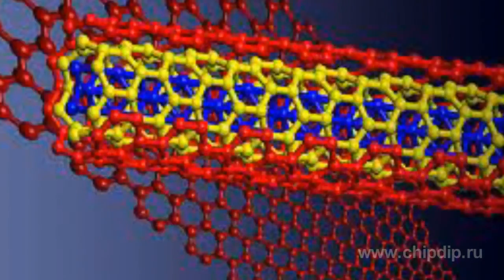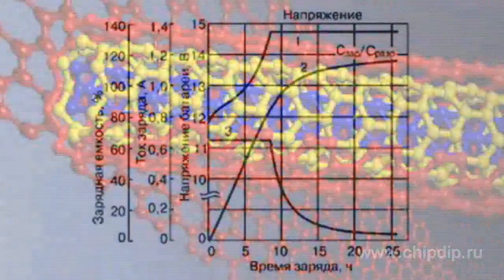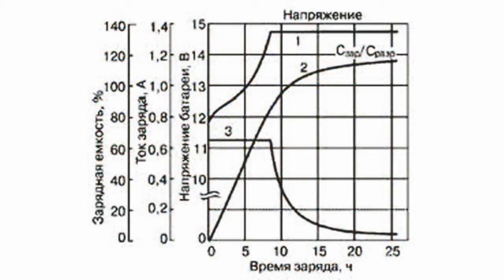The large size of the cavities — about 30 nm high and 150 nm wide — provides free in-leakage of the electrolyte, allowing ion transport of lithium both outside and inside the channels. This significantly reduces charge and discharge time. Additionally, this material has large specific capacity and good cycling due to its stable structure and high ionic and electronic conductivity.